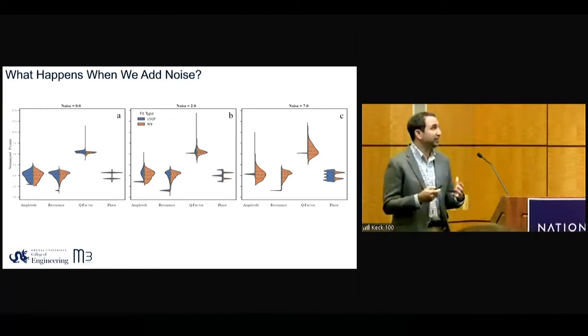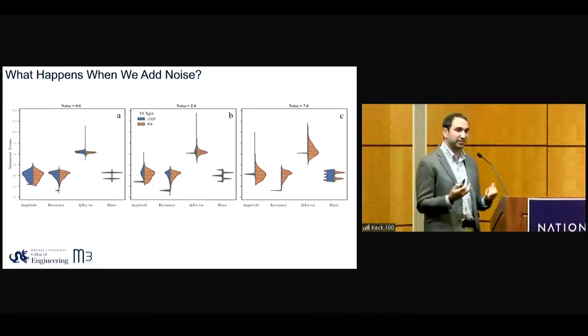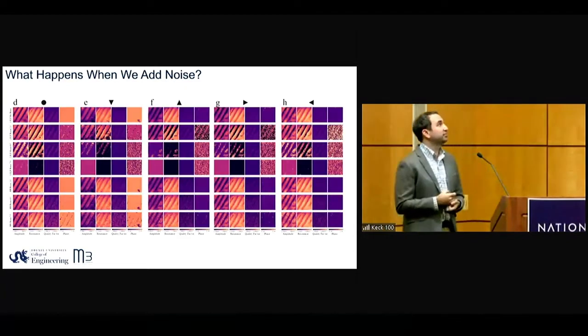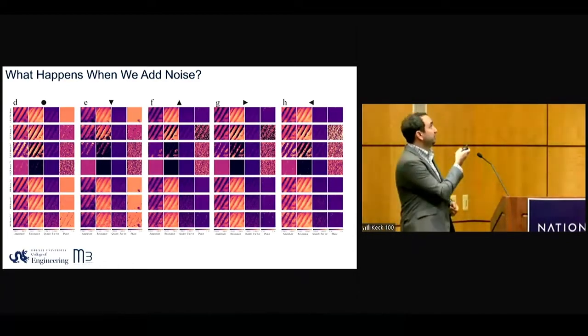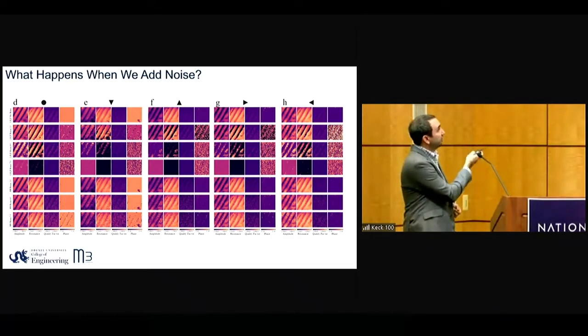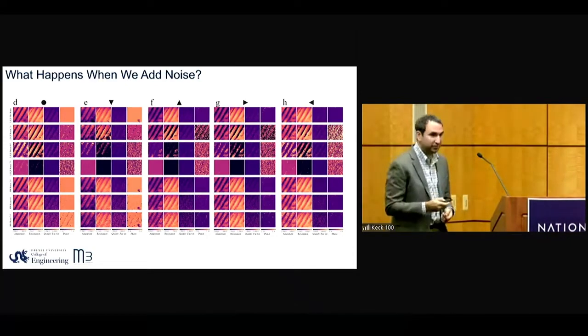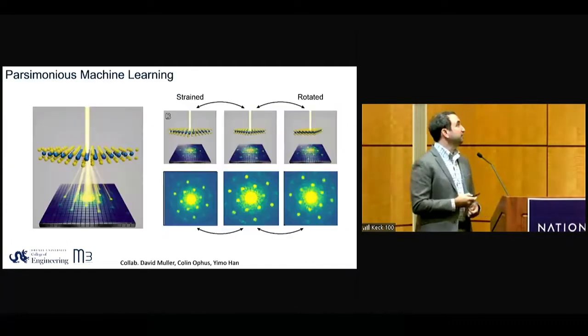So what this is showing is that the neural network is able to be much more resilient to the noise in the data. And we'll show more examples of that. Down here is the least squares fit of the noisy data. It doesn't show anything, but you still see the domain structure. This means you can deal with much lower signal to noise ratios by using neural networks in creative ways.